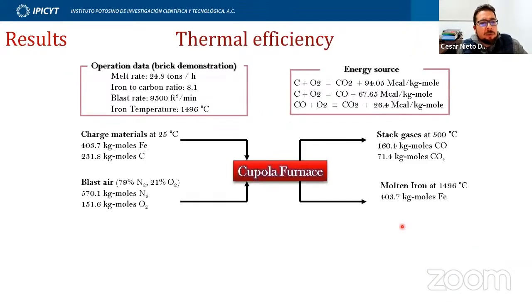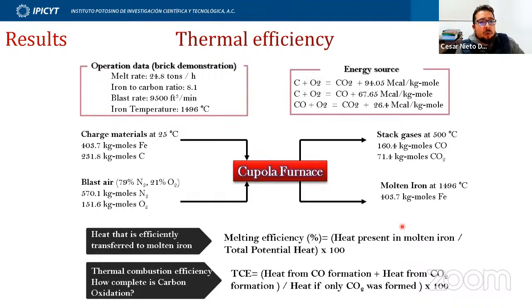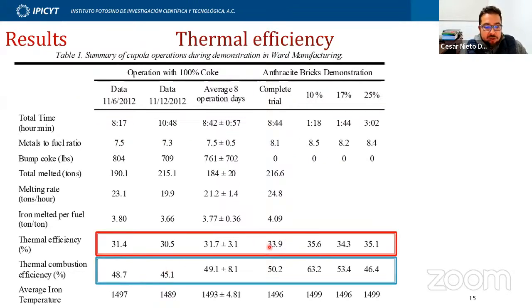Now, we also made a mass balance and energy balance of how well the heat of the fuel was transferred to the iron. I am not going into detail on these equations and this mass balance, but just remember that the melting efficiency is how the heat is transferred to the molten iron, and the TCE, or thermal combustion efficiency, is how complete the oxidation of the carbon is. You can see those values in this table. The thermal efficiency is higher when you are using anthracite bricks, which means that the energy is transferred more efficiently when you are burning anthracite bricks instead of coke. And also the thermal combustion efficiency was significantly higher.